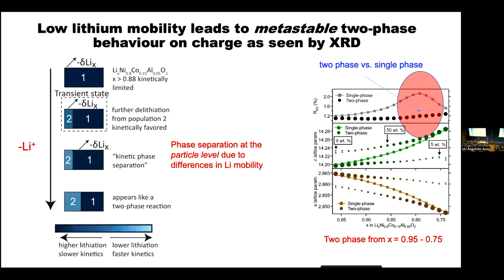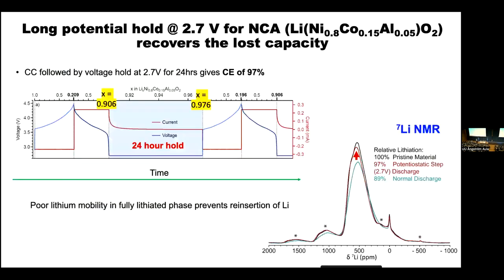Just using the ideas I just developed from the LCO case, you can imagine a scenario where you have a very poor lithium mobility phase. You start to pull the lithiums out of the structure to form phase two. The ions are moving fast in phase two. It's easier to pull more lithiums out of that phase than it is to pull out of phase one. And so you develop this metastable two-phase reaction. And this is just to show that when you go back, you can put the lithiums back in again, and you can see that by NMR spectroscopy.